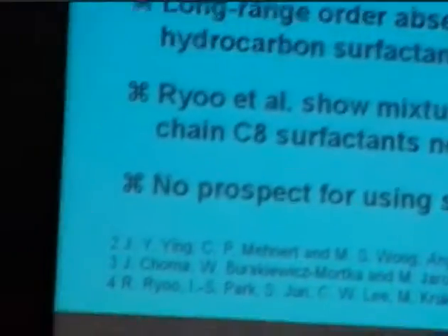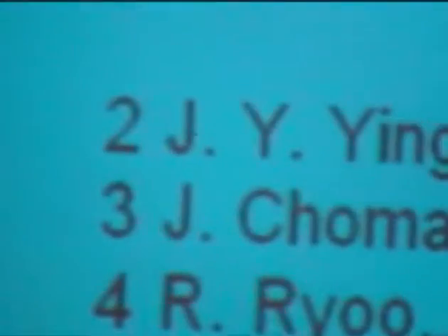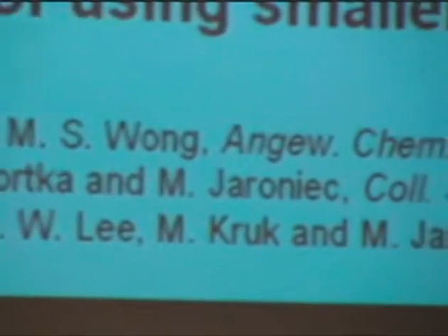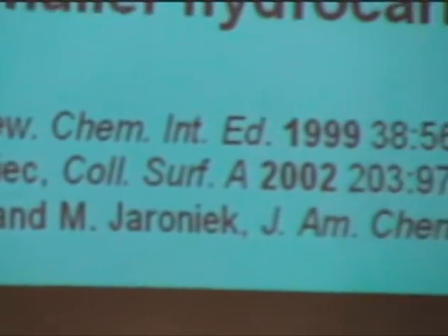And this is an example of a carpet of nanotubes that was created by first making one of these ceramic materials, putting catalyst into it, and then growing the nanotubes. And you get a very regular array. You can't really see that with SEM, but if you do TEM, you can correlate the pore size of the original material and the carbon nanotube size. So those were just a few examples of catalytic applications, which I went through in a sketchy way, but I just wanted to emphasize that you can use these materials as catalyst supports, of course, and as catalysts themselves.